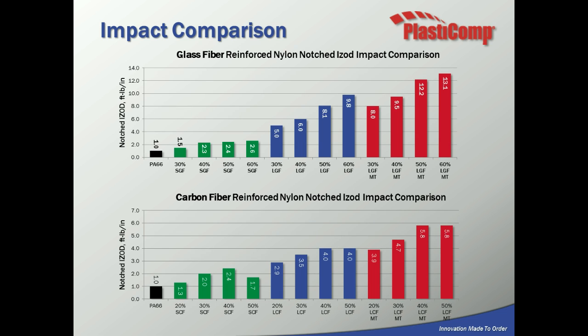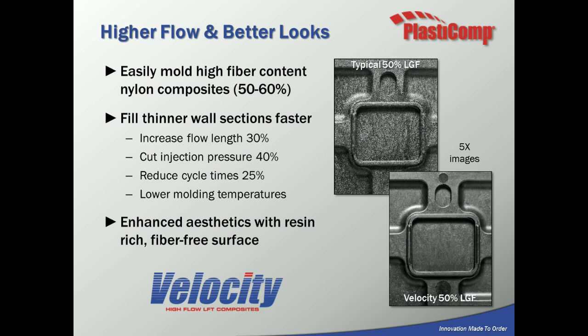And here's some impact data in comparison. Long glass MT products are over on the far right on the top graph, and then on the bottom we're looking at carbon fiber. But as you can see, by the addition of the MT product, we get significantly higher impact values, and that is true in the glass formulations as well as the carbon formulations.